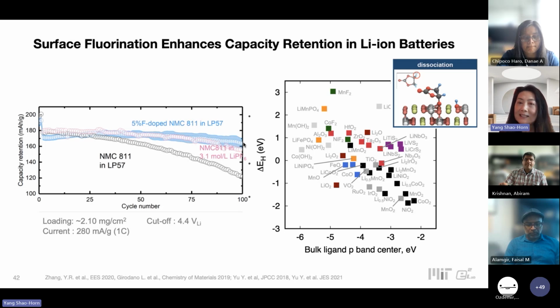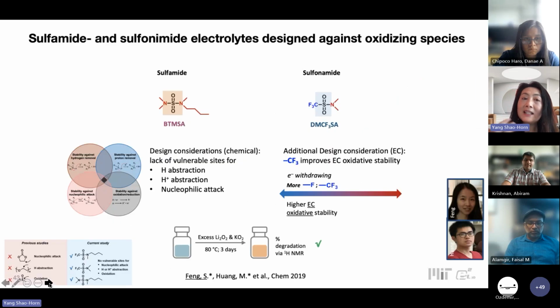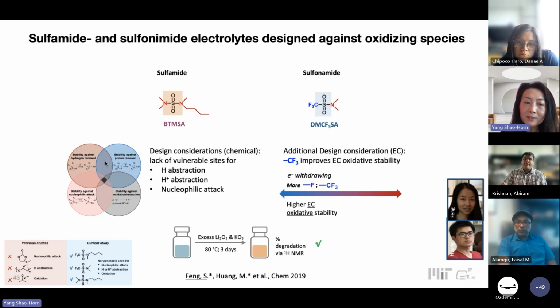On the other hand, we can also test the hypothesis to say, now, what if we maintain these active oxygen sites on the surface, but we change our electrolyte, by developing molecules that can be more resistant to oxidative dehydrogenation. And this is really leveraging our work with Jeremiah Johnson over the past 7 years in developing electrolytes for lithium oxygen batteries, right? We want to develop liquid electrolytes or solvents that can be stable against superoxide, peroxide species. And so we developed a framework for how to think about molecules and the stability of the molecules bond by bond. And we look at it computationally and experimentally, at their stability against hydrogen removal, proton removal, bond by bond, as well as stability against nucleophilic attack and electrochemical oxidation.